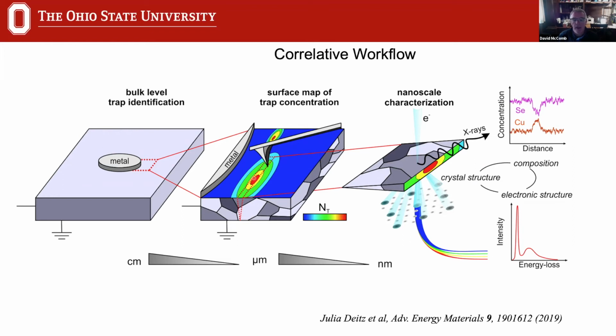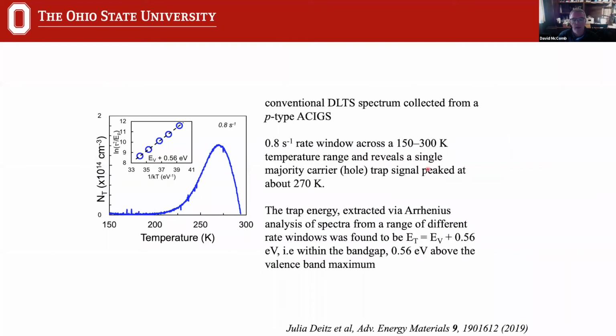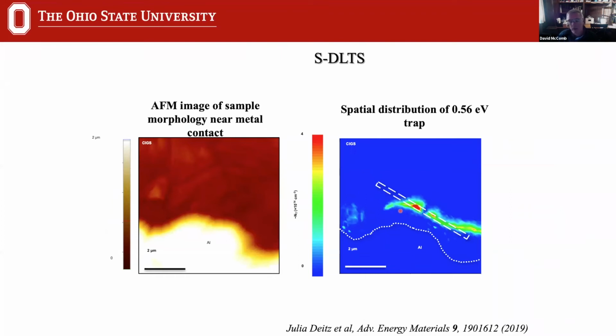below the surface in this device, and then to lift a FIB sample from a very specific place, directed by our scanning measurements, and then to go looking for those defects within this lamella that we've lifted out with the FIB, in order to see if we could identify them. Again, in the interest of time, I'll skip over some of the details here, but this is the scanning DLTS that shows us a particular defect that is a 0.56 eV trap that's well known in this type of device. This is a map of where the intensity in the DLTS actually is, and this is the scale of the FIB foil that we're then going to lift out.